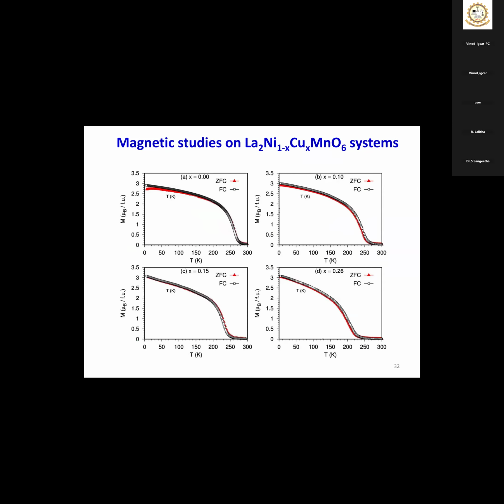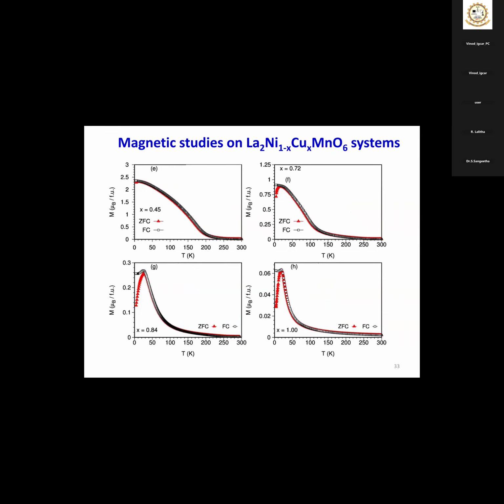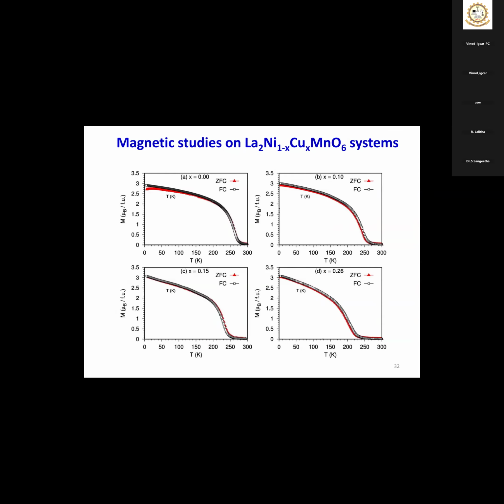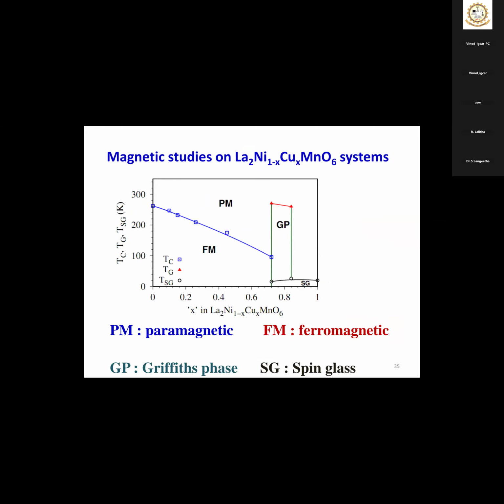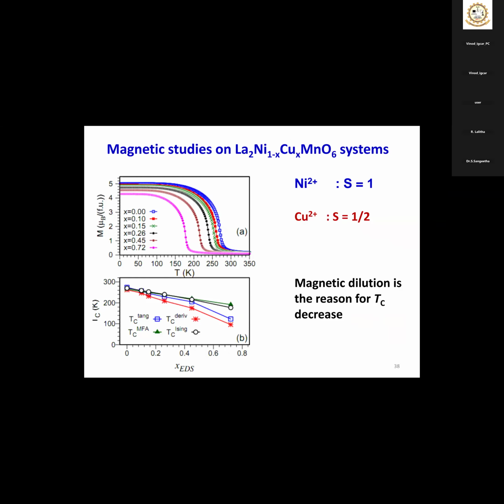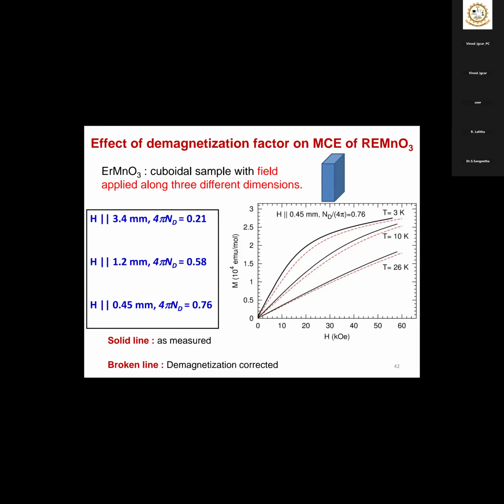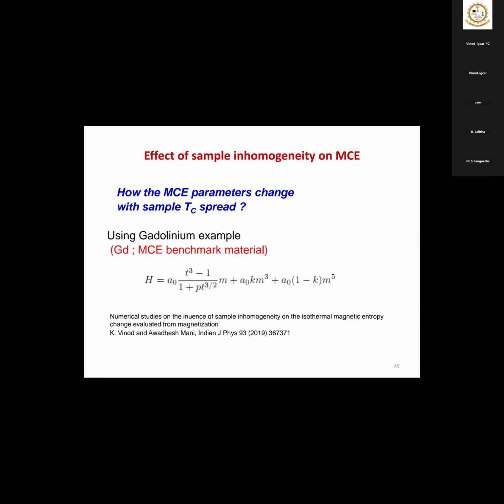Here you can see for the low copper content, the transition is relatively sharp. As you increase the copper content, slowly the transition is broadened. Here you can see it is highly broadened. The ferromagnetic transition is also broadened, so the TC is also broadened. You can see there will be a TC spread in the sample. This is related to the sample inhomogeneity, which is the most crucial factor. So we want to know whether the sample inhomogeneity will have any effect.